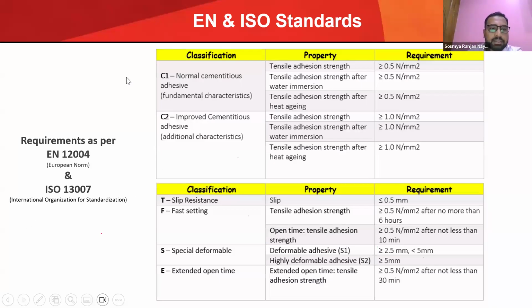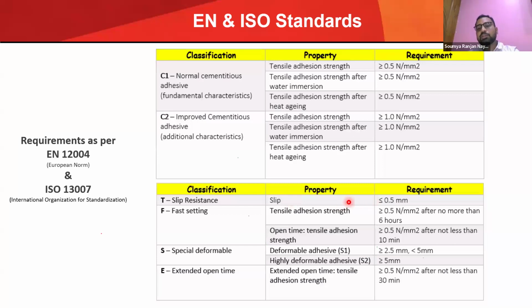If you see here, yeah, now let me take the laser pointer. Yeah, this is the slip resistance. It means when you apply a tile on a wall, immediately after application, the tile must not slip more than 0.5 mm. It's very difficult to measure from the naked eye, but this is the criterion a tile adhesive has to maintain. That's why we are saying we have to shift from cement to tile adhesives, because these are meant for tiles. Otherwise, what will happen? You keep on fixing the tiles, and the tiles will slip one by one, and you will never get proper lines in fixing of tiles.